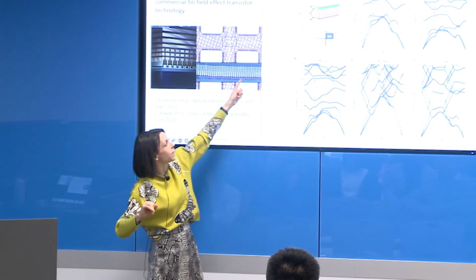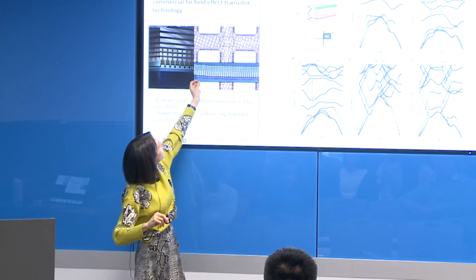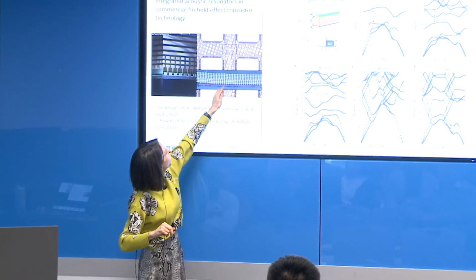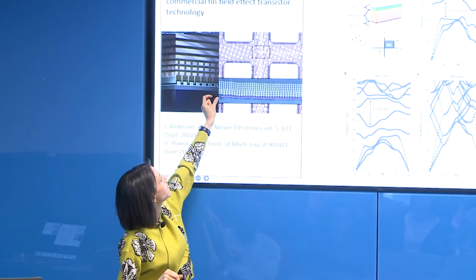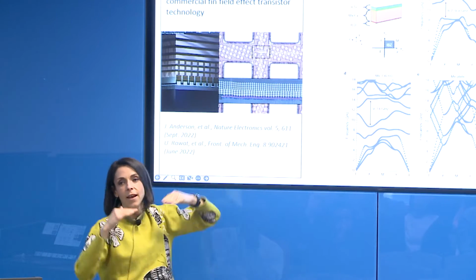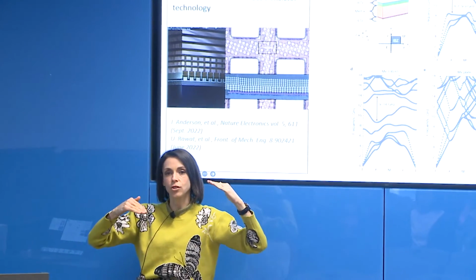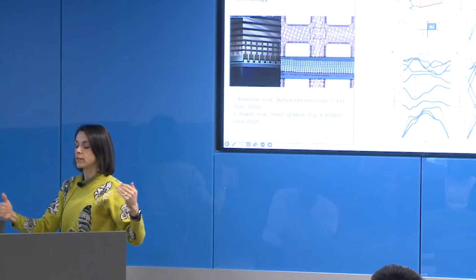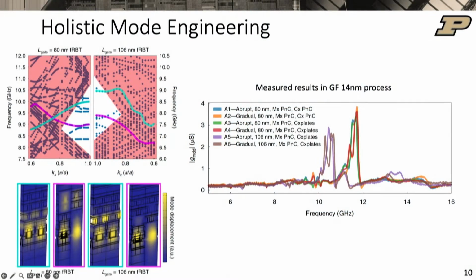And so if I change the periodicity of these structures, this is a wavy picture here because that's just the way the SEM came out. But you can see that I have a particular width to these devices, and it gets a little longer here. And that's to give us this mismatch, and is in fact an adiabatic transition in that case, from where I want the resonance to exist and where I don't, where I want it to terminate.